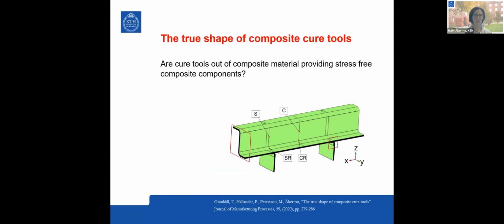Often you think that if you have a composite material, which moves differently in the plane compared to the out-of-plane, cure shrinkage and thermal expansion is totally different from the in-plane. But normally what we used to say is that if you have a tool that behaves the same, this will not be an issue. The tool-part interaction will be reduced. However, when we make a composite cure tool, we cannot make a tool that is only like a U-beam as the component we want to produce. We need to stiffen it up with some backing structure.